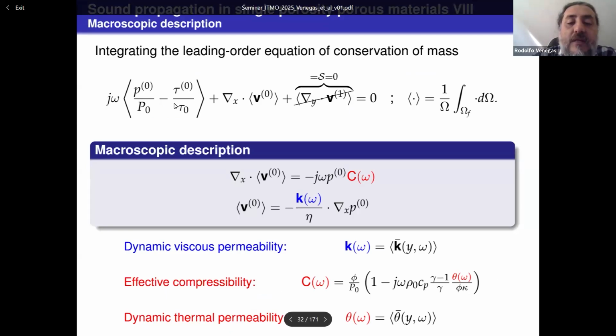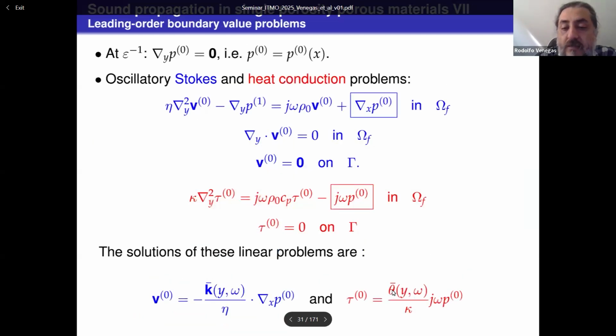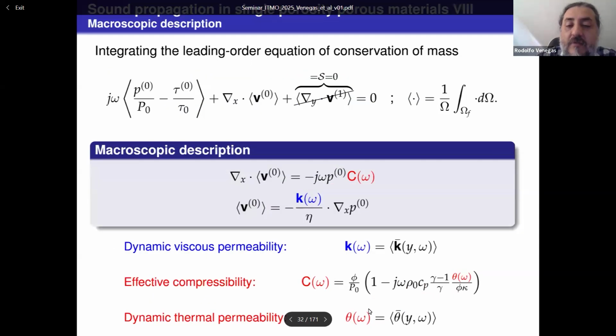So for this term, we can do a little bit of algebra and write it in this way and define the compressibility as it is shown here, which depends on the dynamic thermal permeability, which is the spatial average of this local operator here. So what we do is to say P naught is equal to 1. We solve the problem for temperature. Since we know P naught, we solve for the temperature, and we know the rest of the parameters. We know the local operator here. We take the average, and then we get the dynamic thermal permeability.